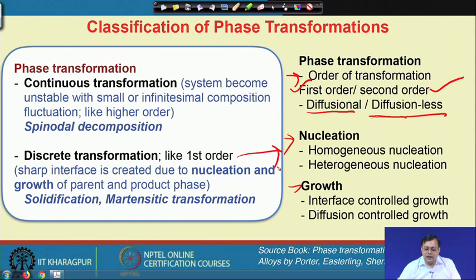Okay. In that particular case, we may get a more homogeneous microstructure, but if we chill or if we cast a cast iron or let us say aluminum alloys in a cast iron block mold, then we will see that three different layers appear, because the solidification has initiated from the chilled layer. So, there the cooling rate is faster and heterogeneously the mold surface also acts as a heterogeneous site for nucleation, and therefore, the nucleation starts from the surface and requires less activation energy, whereas homogeneous nucleation requires higher activation energy, because you have to create a surface and creation of a surface requires excess energy. However, in case of heterogeneous nucleation, the surface is already there, only some atoms have to move and it needs less activation energy. So, that is more favored.